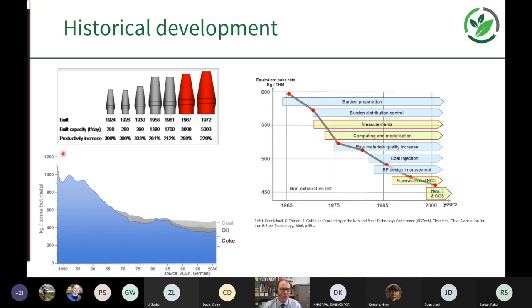It's a massive scale, and it's an industry that's really improved its efficiency through scale. On the bottom left hand side there, we've seen some real big improvements in efficient use of raw materials in the blast furnace. Quite significant reductions, but as I mentioned earlier, the rate of reduction in the amount of material going into the blast furnace has slowed down. We're approaching the thermodynamic limits of the process. And then on the right hand side, we've got technological developments in comparison with the reduction in the equivalent of the coke rate, so quite significant reductions in the amount of coke going into the process, and that's been an important development in improving the efficiency of the blast furnace.